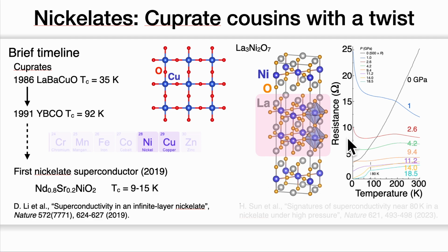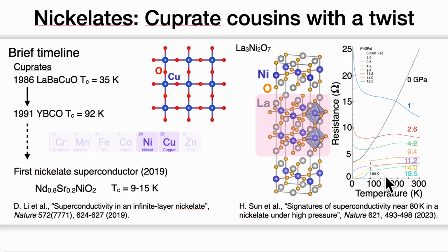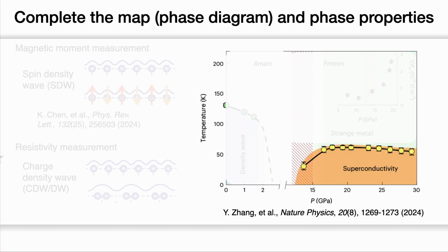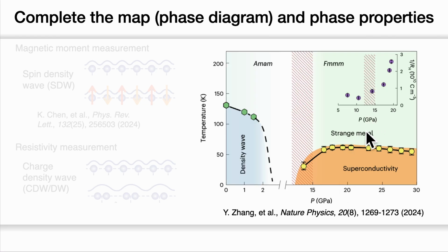Its resistance as a function of temperature is shown here. As we can see, when we increase the pressure, its superconducting behavior emerges and has a Tc near 80 Kelvin, entering the high-temperature superconductor family. Since then, during these years, people have started to look into the phase diagram of LNO and found, for example, strange metal and the density wave next to the superconducting phase.